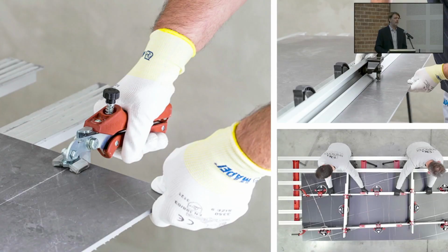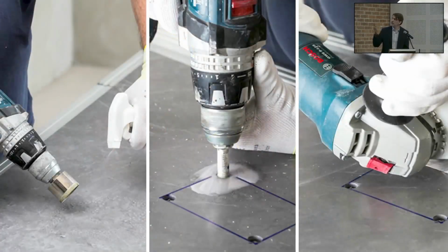And also when we have to cut them, we need special support, special tables and tools to provide a clean, defect-free cutting or edging of the material, even providing some special holes and elements in the tile itself. I just say this because we experience many times in Italy that even before choosing the fixing system, even before the adhesive or the substrate, the tile is already broken. And in this case, there's nothing you can do. No epoxy resin, no elements can repair a defect given by the wrong handling of the material.